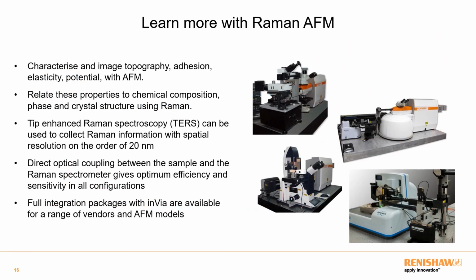Now I want to move on to Raman AFM. The nice thing about AFM is you can characterize and image things which are very different to Raman spectroscopy. So things like topography, adhesion, elasticity, potential, all with very, very high spatial resolution. So relating these properties to the stuff you get from Raman is very useful. In addition, using an AFM and a Raman system in combination lets you do something called tip-enhanced Raman spectroscopy, and that can be used to provide Raman information with really high spatial resolution, so on the order of 20 nanometers. We work with a wide range of AFM vendors, and they can all be coupled to our Raman system, and they all have their various different pros and cons depending on the sort of samples you want to look at.